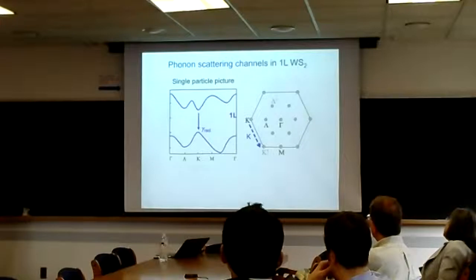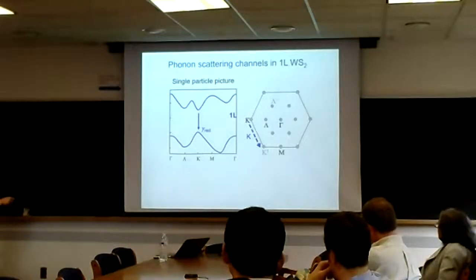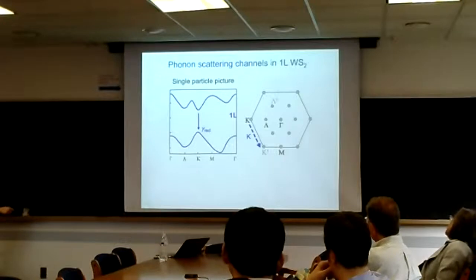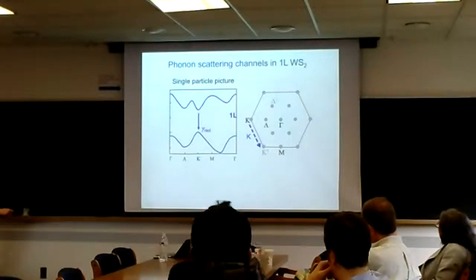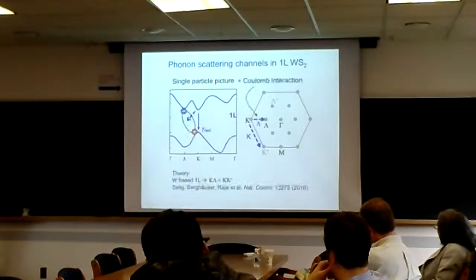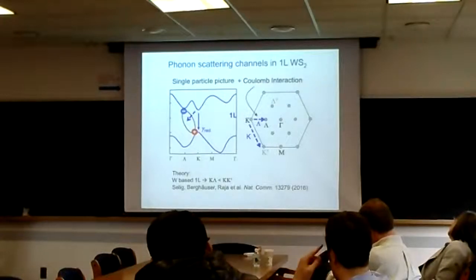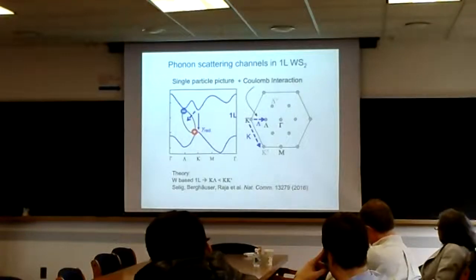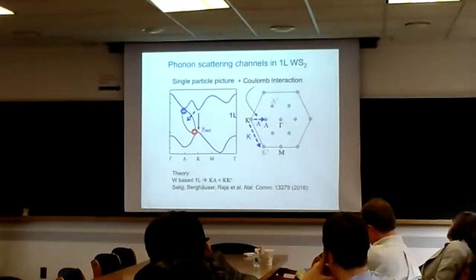So in the single particle picture, without turning on the Coulomb interaction, and without spin-orbit coupling, which I'm not showing here, you have the band structure like so. You have the direct gap at the monolayer, and essentially only scattering from K to K prime and within the K valley. Now, when you add Coulomb interaction, however, we showed a few years ago in an experiment-theory collaboration with Andreas Knorr and Ermin Malic that you have a new dark state. Because the lambda valley effective mass is heavier, you have higher exciton binding energy, and so you have a new dark state into which this direct exciton can decay.